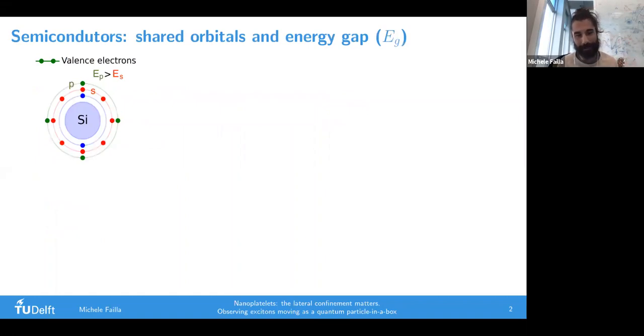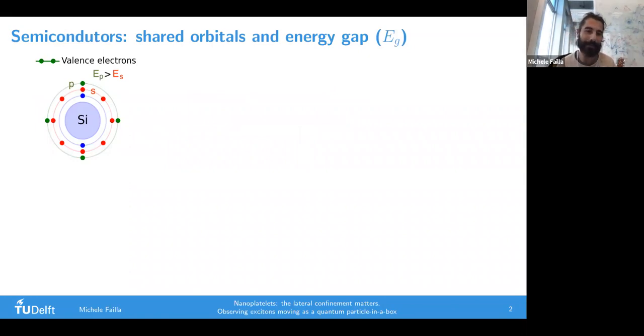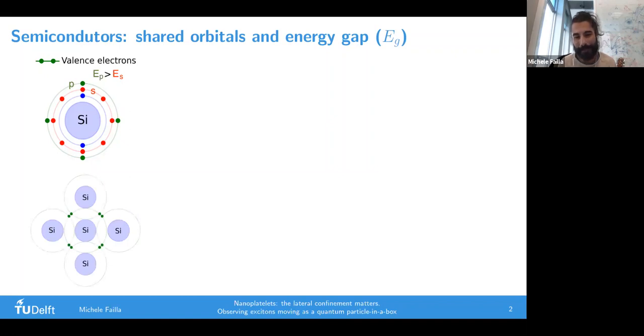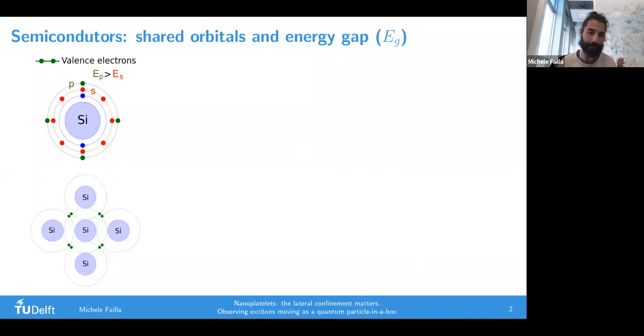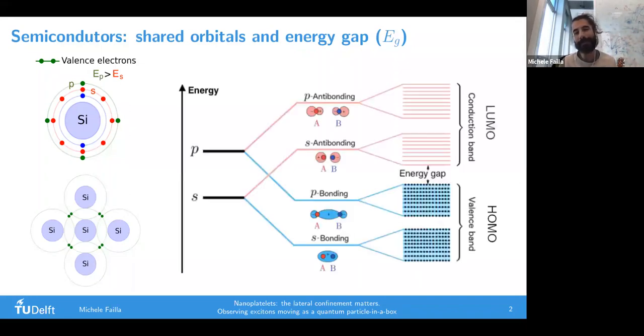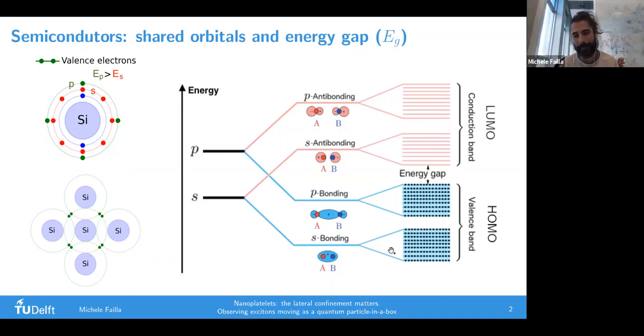Let's start with semiconductors. Let's take the most common semiconductor element, silicon, and consider this orbital scheme of the silicon atom - you have the S and P orbitals. What happens is that as soon as you bring together different atoms to form a crystal, the electrons start to get shared along these different atoms. This sharing of orbitals causes the P and S orbitals to form bonding and anti-bonding combinations, forming two different bands called the valence band and conduction band.